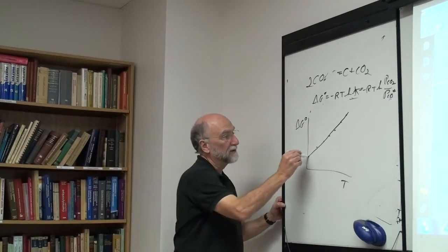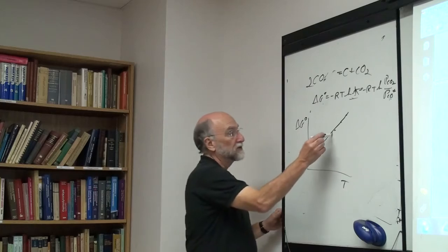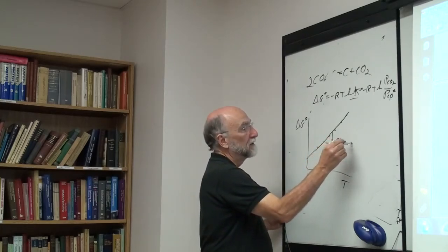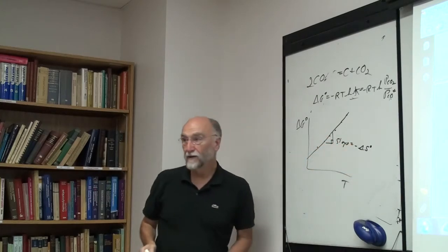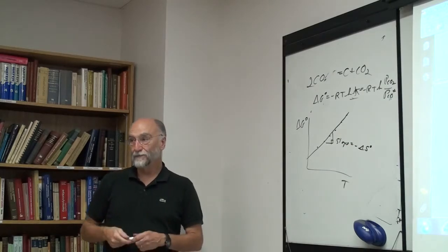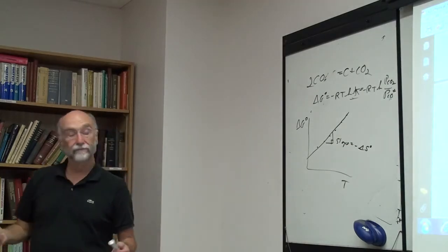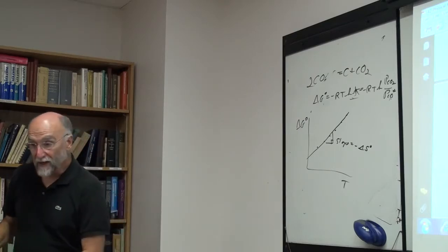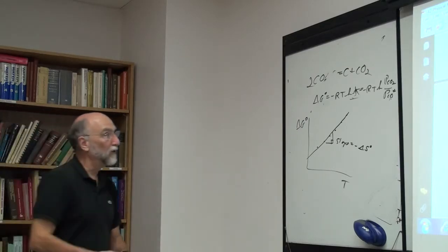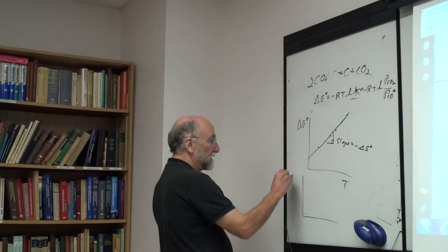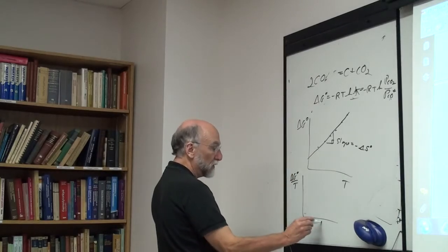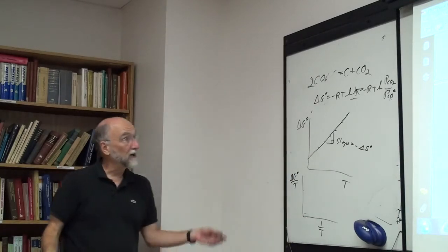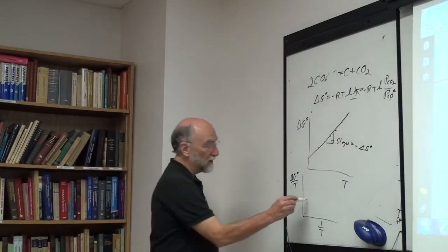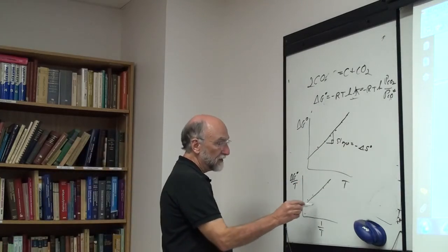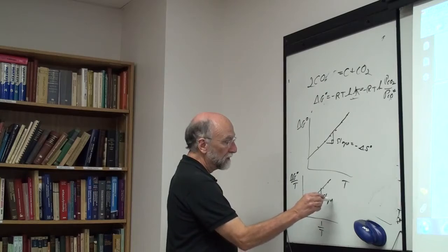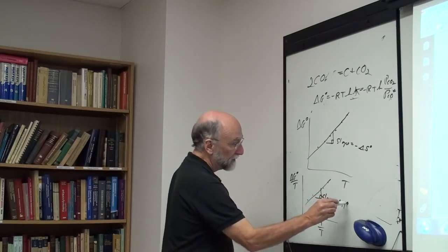And then I draw a line through here and the slope of the line is minus delta S of the reaction. Okay, so you can measure delta S of a reaction by measuring the slope. Or let's do it differently. Let's plot delta G naught over T versus 1 over T. Just another way of plotting the same results. And now I got a line here. And if I draw that line, the slope will be equal to delta H.